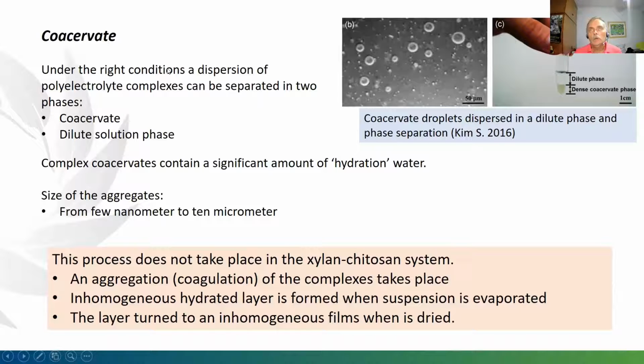We could expect to obtain a coacervate phase in this system, because under the right conditions, a dispersion of polyelectrolyte complexes can be separated in two phases, a coacervate phase and a dilute solution phase. And these coacervates contain a significant amount of hydration water. The size of this aggregate could be from a few nanometers to 10 micrometers. But this process doesn't take place in the xylan-chitosan system. An aggregation or coagulation of the complex takes place. As a consequence, an inhomogeneous hydrated layer is formed, and later the layer turns into an inhomogeneous film on drying.